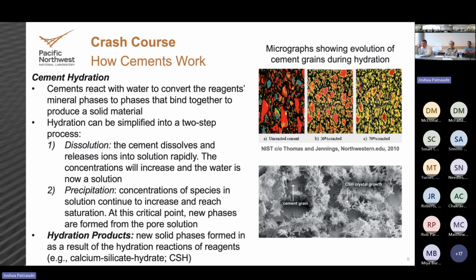The design in the top right is probably clear on the paper slides. It's showing an image of the progress of reacting cement grains over time. Those red pieces are actual fine cement particles, unreacted. In the middle, once you've added it into water, the yellow are the hydration products that are starting to form as those grains start to be consumed. Then as time goes on, you get more of that yellow, and those hydration products grow. Eventually they grow out and link together with one another, and you end up with microstructures that look like the electron micrograph in the bottom right, where those flat areas are the cement grains, and all those needle crystal-like structures going in between are the hydration products. As they grow out, they link together, the grains become locked in, and that's how you convert into a solid mass.